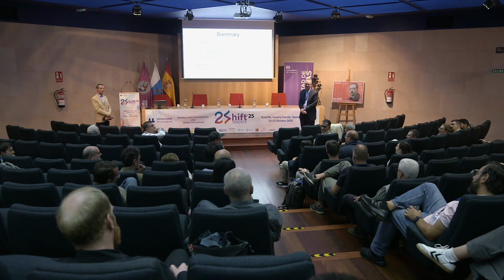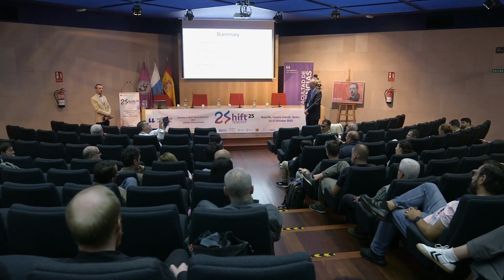Now, if I look at your experiment activating calcium tungstate with ytterbium-3, you have wonderful properties useful for quantum technology, but yet you have a host compound where you have some charge compensation going on. Is that actually an issue, or have you seen any indications in your experiments that ytterbium-3 going on the calcium-2 site, for instance, does cause problems that you still have to get rid of?